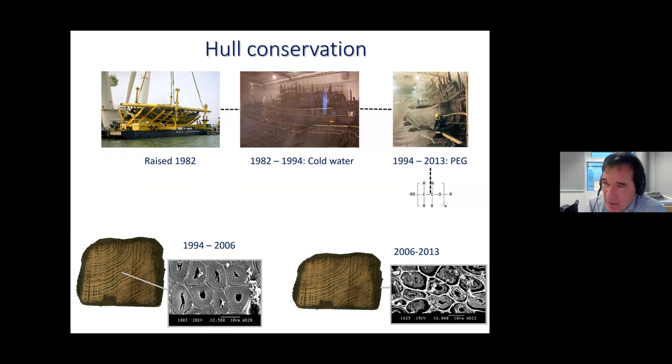And the process for preservation actually was pioneered in Sweden. So a few hundred kilometers away from where Christine is at the moment in Copenhagen, they pioneered a technique to preserve the wood of the battleship Vasa. And what they did, and our collaborators copied this process, is they replaced the water by a heavier molecule called polyethylene glycol. And that infiltrates the wood.